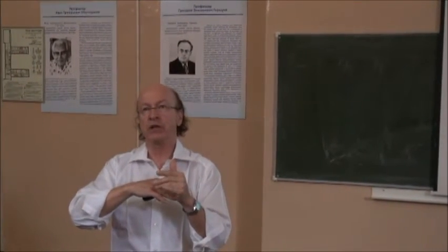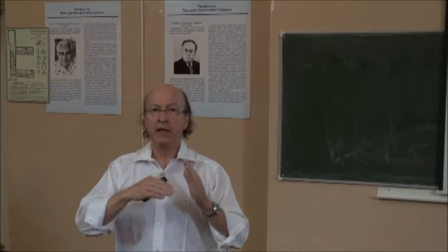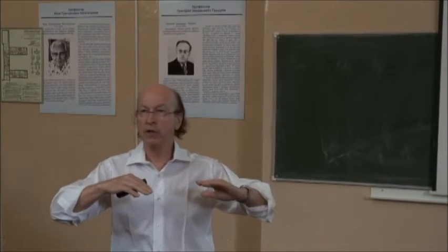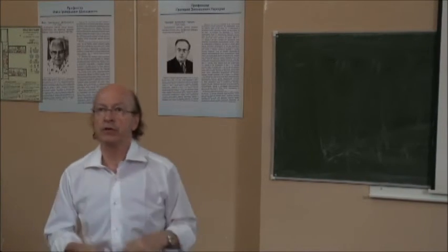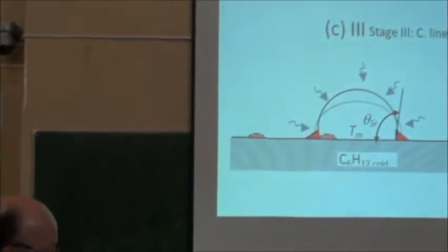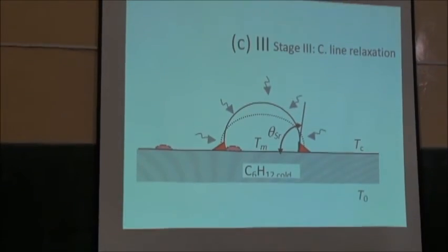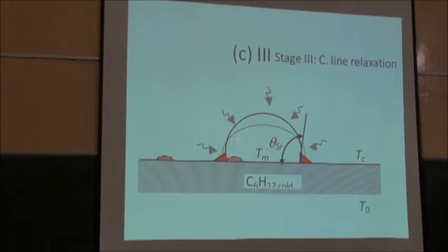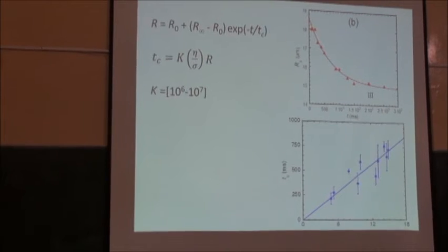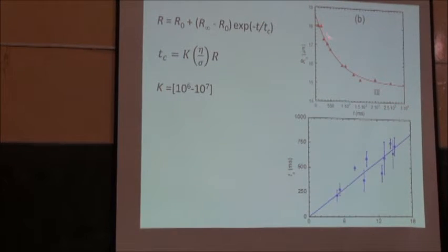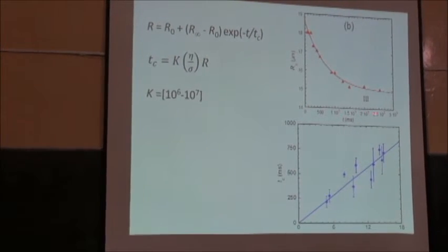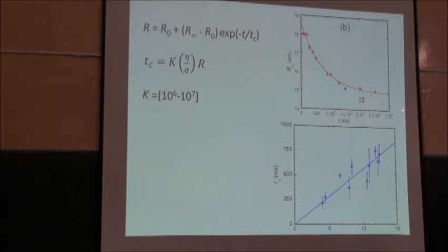And this paradox can be solved by telling that the motion of the contact line is due to a phase transition. That is, you have molecules, you have evaporation, condensation, evaporation, condensation. And we know that this process is a slow process. That's why, for the relaxation, we go from this position to that position, and that's a very slow process. That's an exponential, so the radius is decreasing with time. You see now that's not milliseconds, but that's 1,000 milliseconds. That's 3 seconds. That's very large.